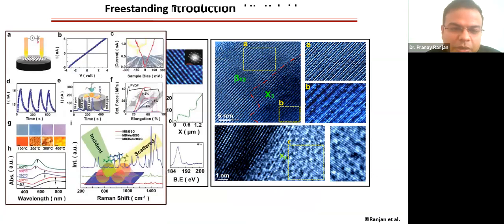However, we tried different kinds of applications, and we found the metal to be phenomenal, because even at room temperature, there is a density of states clearly shown in image C, where we got the quantum state at room temperature. In B, you can see that even at room temperature, it's metallic in nature. That's a very different kind of material which we are talking about. That is a metallic 2D material, which is a new class of material.